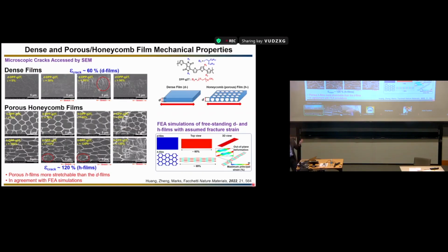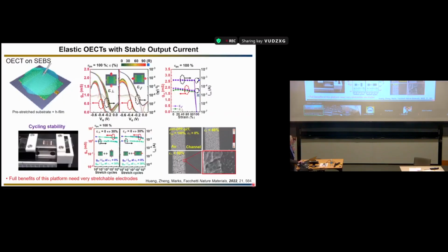Basically, this honeycomb morphology, which has been used widely, for example, in aerospace technologies to enhance ductility and mechanical energy dissipation, applies also to this organic. So you get better ion intercalation and better ductility for the same polymer when you use this honeycomb. So we can make these devices which can stretch, and the current is stable.